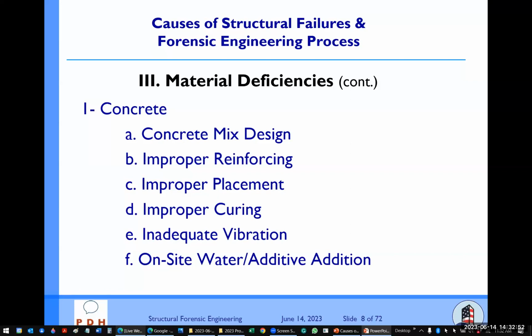Sometimes you have to get the record of even the mixer trucks that they bring in. And then there are reinforcing issues: improper reinforcing versus improper placement. With the placement, obviously, whether it's a negative rebar or a positive rebar, if the D distance in a 12-inch slab is changed by 1 or 2 inches, it can make a big difference. I've seen that in some cases when you do GPR, ground penetrating radar verification, that the rebar placement is off by like 2 inches, causing problems, cracking and other things.